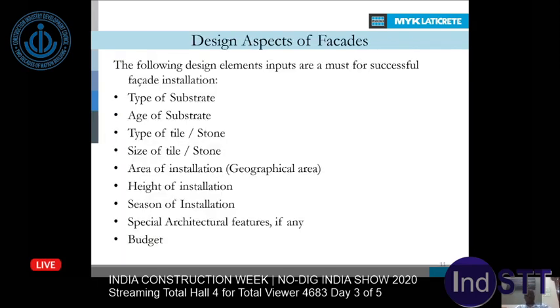And when you go with the facades, there are a lot of designs that go with that. That should be kept in mind when we select the right tile adhesive or material to fix the stone or tiles. We have to make sure what type of substrate, whether it is a highly absorbing substrate or no absorption, and what is the substrate aging, whether it's old construction, then you may see a lot of cracks, and make sure that cracks are filled in so that you get better adhesion and tile durability. And what kind of tile or stone you want to use, whether highly porous or highly vitrified dense tiles or stone. Then what is the size of the tile and stone, that again matters.